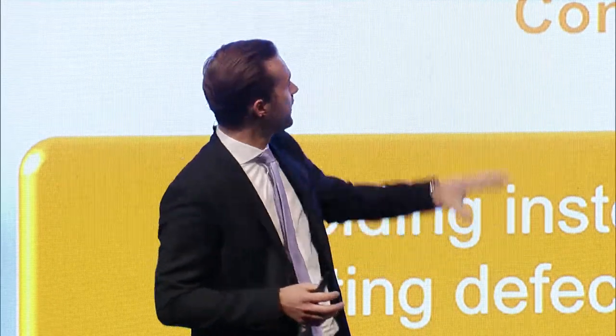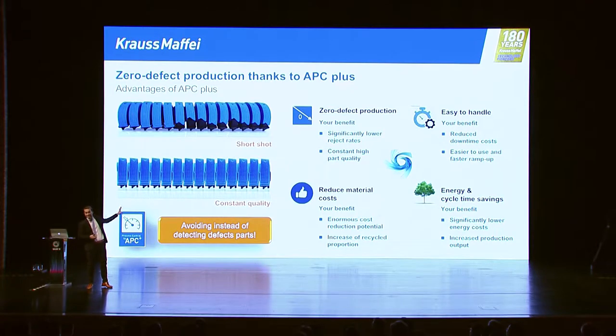All of these have an effect on the viscosity of the material. And during injection molding, normally the switchover point from the screw, from injection to holding pressure, is controlled by the position. And that's the same for every shot. And now, if you do not have a look at the viscosity, your cavity might be filled more or less. And this is what APC Plus is doing. We are analyzing the viscosity of the material in each shot and do not produce a bad part with this.